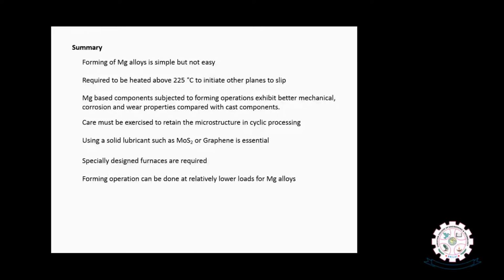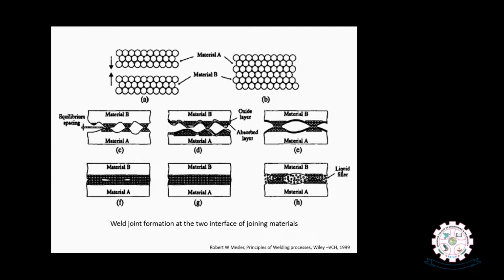Using a solid lubricant such as molybdenum disulfide or graphene is essential in the deformation of magnesium. Specially designed furnaces are required, where we should provide heating as well as mechanical loading in parallel. So forming operations can be done at relatively lower loads for magnesium alloys compared with other non-ferrous alloys, which is an advantage. Welding of magnesium can be done with the conventional welding processes, both fusion and non-fusion welding processes, with a few technical challenges which can be addressed by taking precautions that we'll see in a couple of slides.